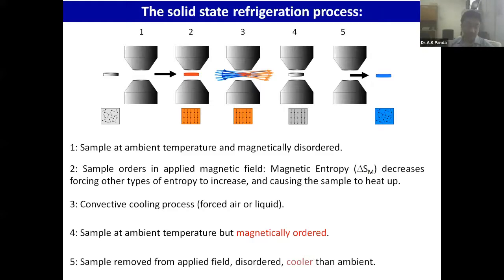There is an orientation of the moments, and therefore the entropy, just keep remembering that it is the magnetic entropy which decreases because we are going to a more ordered state, and that causes the sample to heat up. This is surprising actually. Why at all does it happen?